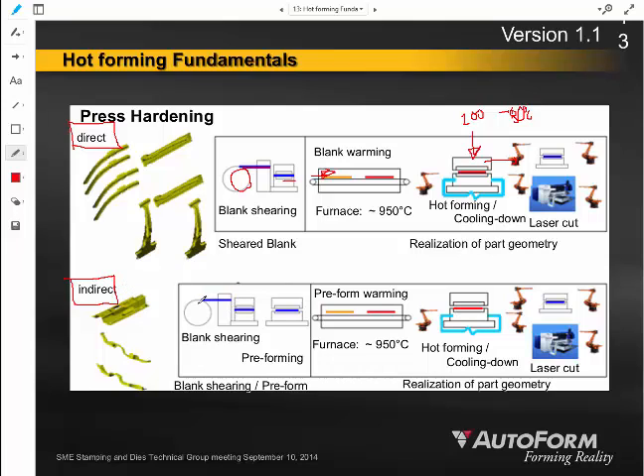Indirect hot forming starts off with the same operation, but instead of going directly from the blanking operation into the furnace, you can actually form that material some of the way, partially, at room temperature. That's going to allow you to make a slightly deeper part without necessarily having a high degree of localized thinning. Right? One of the problems with forming these materials at such high temperatures when we do this direct hot forming is the fact that any thinning that does happen tends to be highly localized. Right? The material is heated up and it's very ductile at that point. And what will happen is that the thinning can get localized maybe in ways that are slightly undesirable.